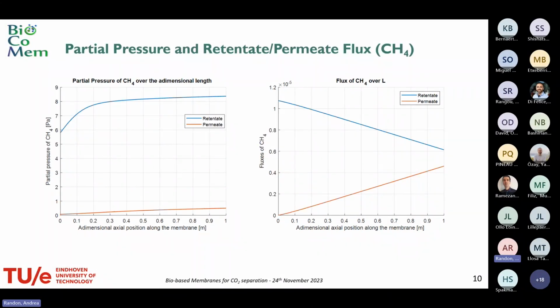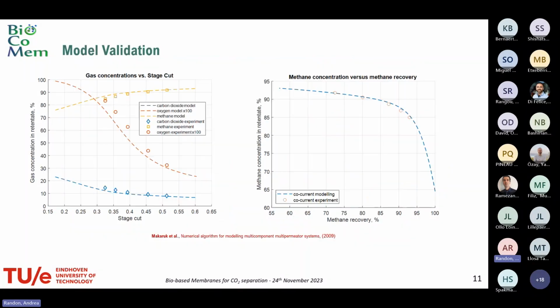And we also checked how the partial pressure of the methane was going versus the dimensionless axial position of the membrane, and the flux as well. Since during the biogas upgrading what you want is an enrichment on the retentate side, as you can see, retentate in blue and permeate in orange, the partial pressure of the methane along the membrane is actually increasing, which is what you expect.